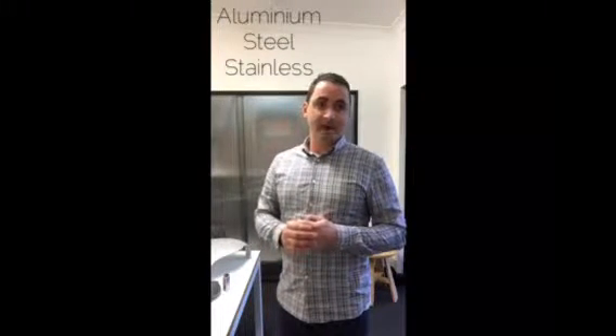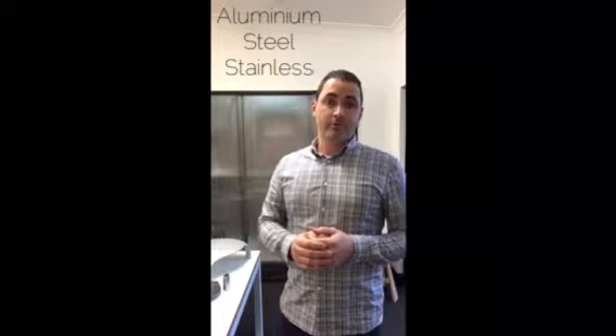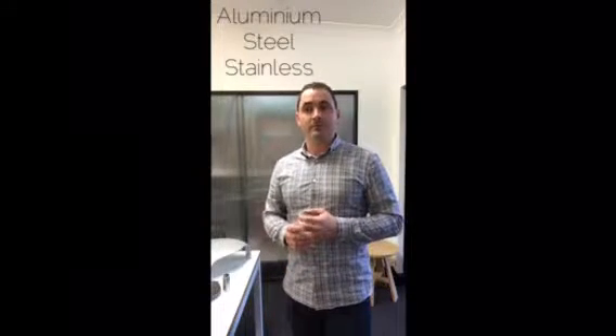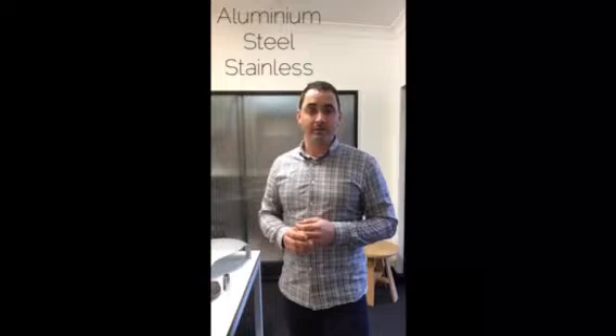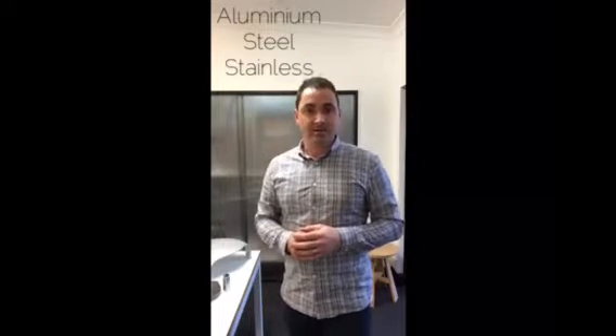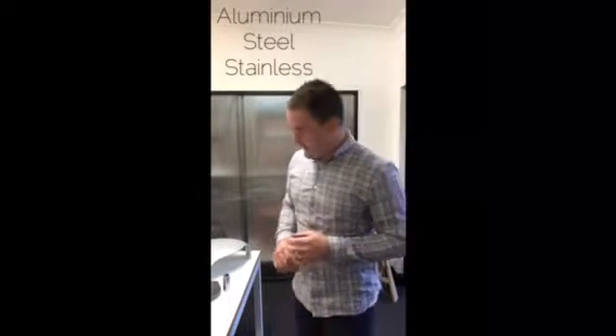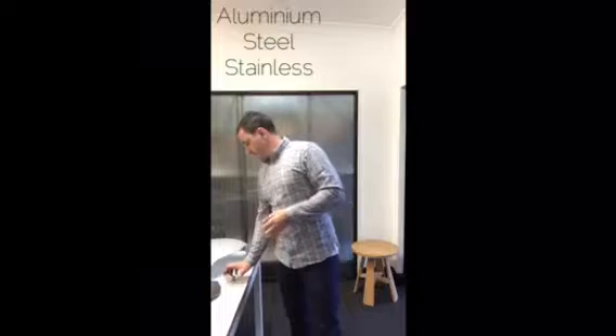The other finish that we have for aluminium is anodizing, which further improves corrosion resistance and also adds some surface hardening of the aluminium. So if scratching and scuffing is going to be a problem, then anodizing helps by making that surface a lot harder. The only downside of anodizing is if there's any welding or linishing that happens to that aluminium, it will show up. The welding adds a different silicon content to it, and so you can see it through the anodizing. So a bit of a finicky kind of process.